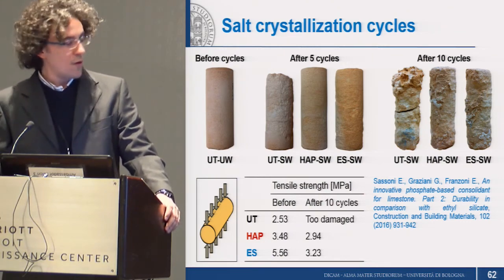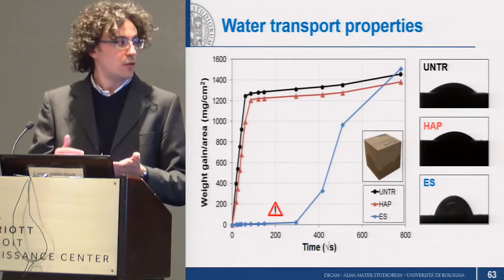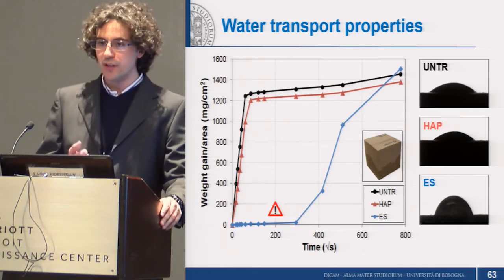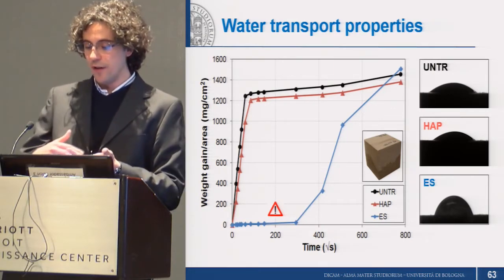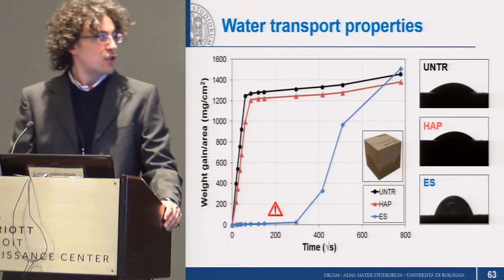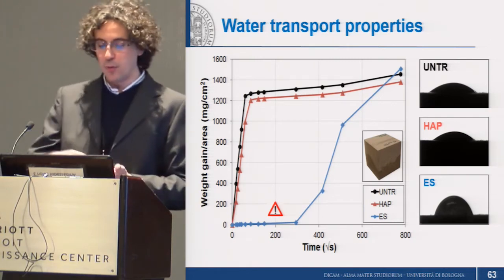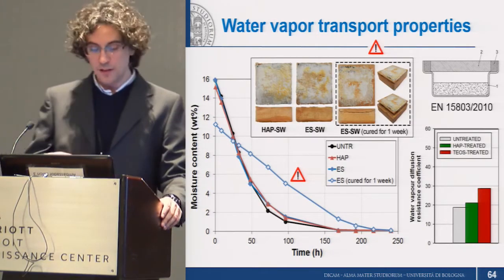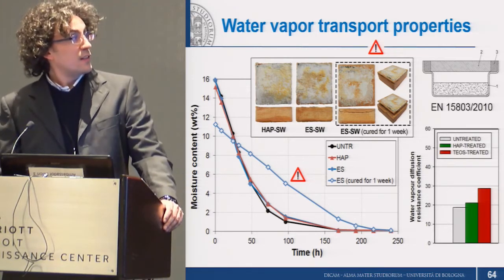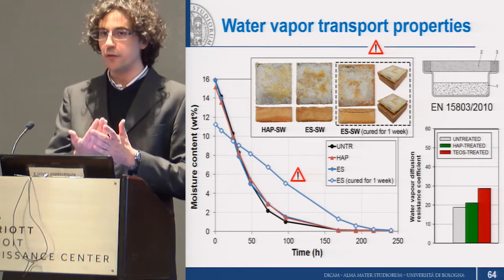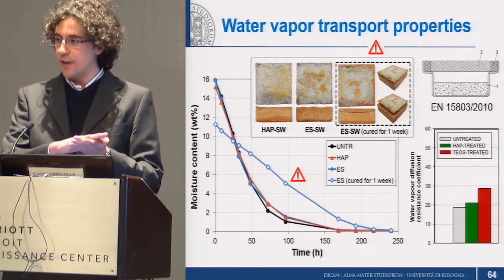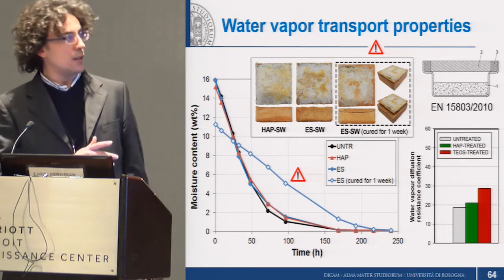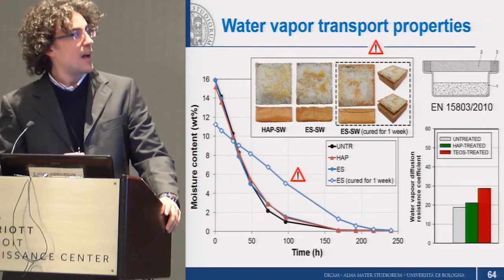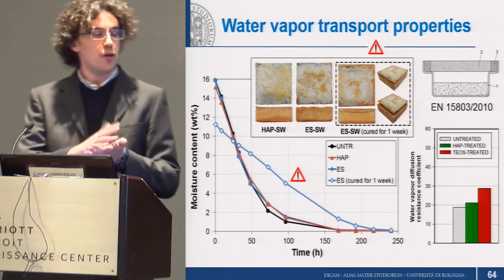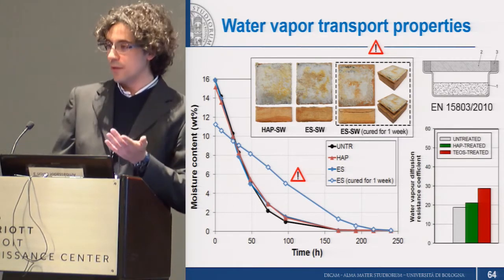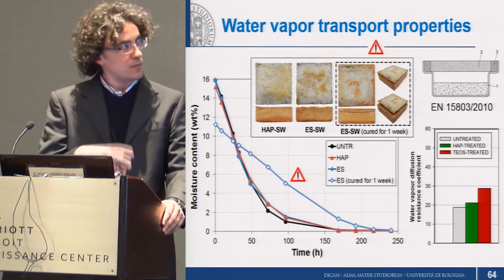Another important feature of our treatment is that it leaves the stone hydrophilic at all stages, whereas commercial treatments mostly cause an initial phase of hydrophobicity in the stone. And this is potentially a very important issue, because if evaporation of water vapor from the stone is inhibited or significantly slowed down, this may be a problem in case water or salt solutions are coming from below the treated surface. So when the treated surface is hydrophobic, as you can see in the square in the top part of the slide, detachment, let's say failure of the intervention, may take place in case water and water vapor diffusion out of the stone is prevented.